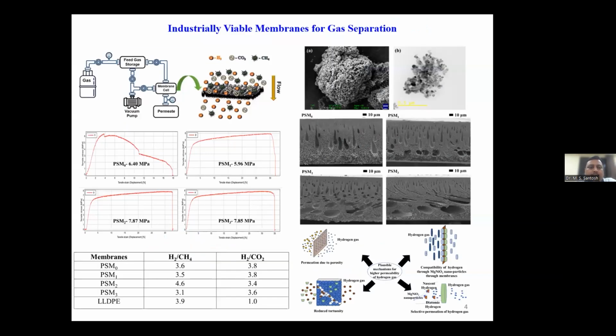So here in this slide, you can see how different characterization results of hydrogen are being showcased, wherein we have a laboratory setup where we make use of a flat sheet membrane, which comes in contact with the hydrogen gas or a mixture of gases, because in this particular case, it is a simulated gas mixture where we have a combination of hydrogen and CO2 or hydrogen and methane together. And since we are testing it out in the laboratory environment, we can only use the simulated gas and not the real gas that is coming out of the gasification process.